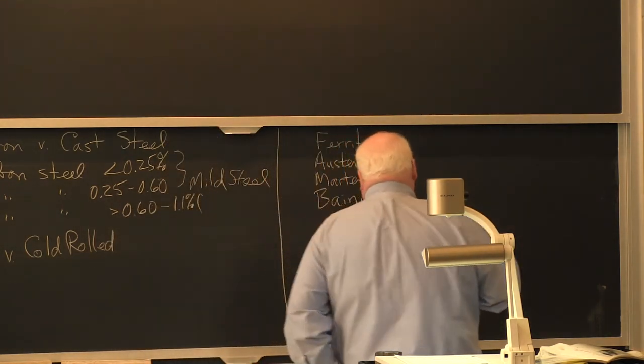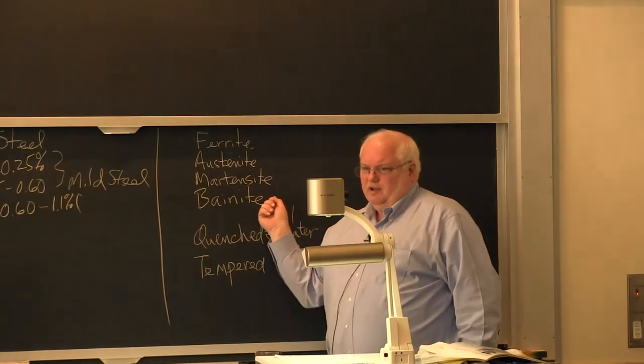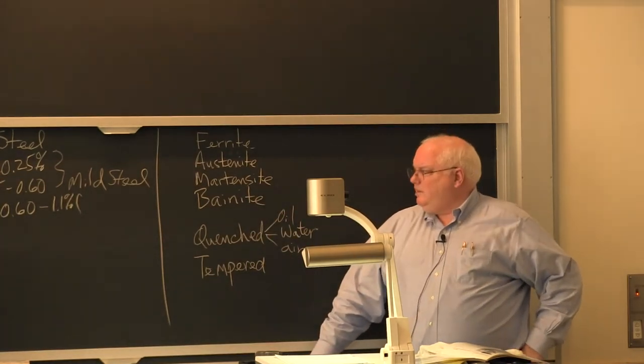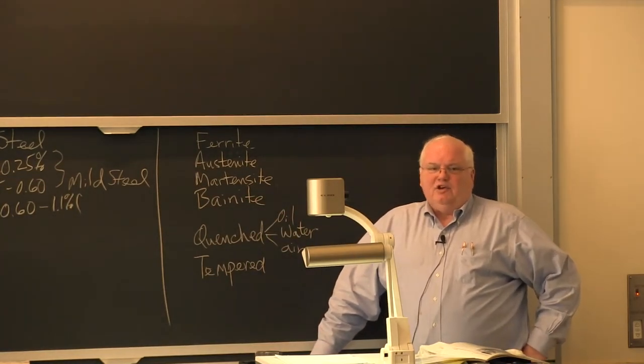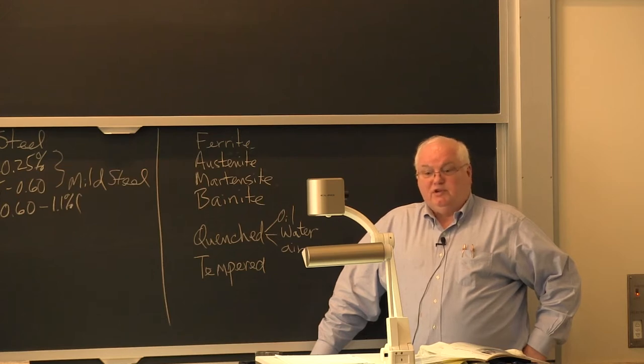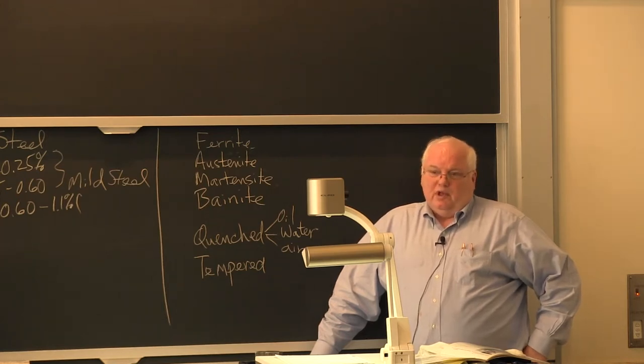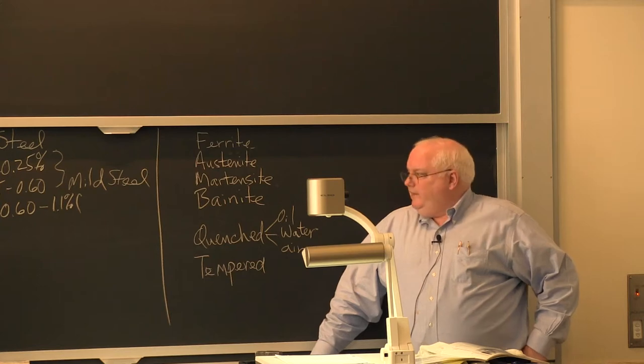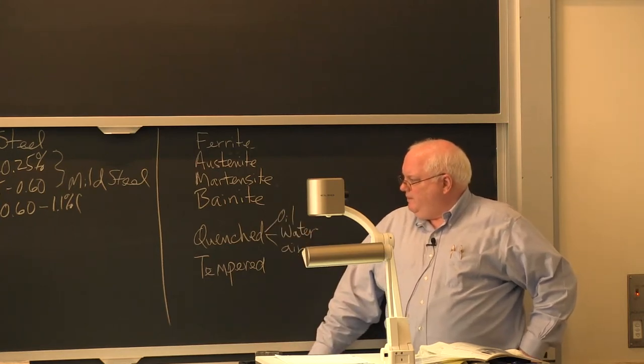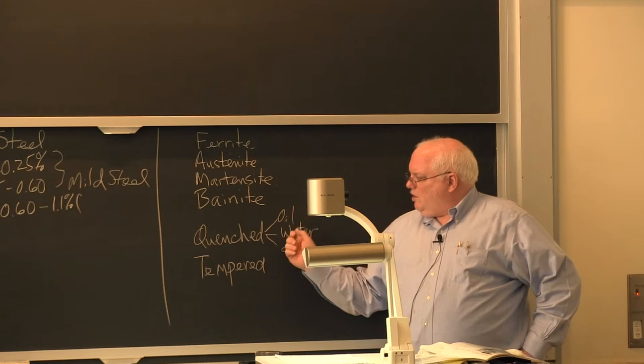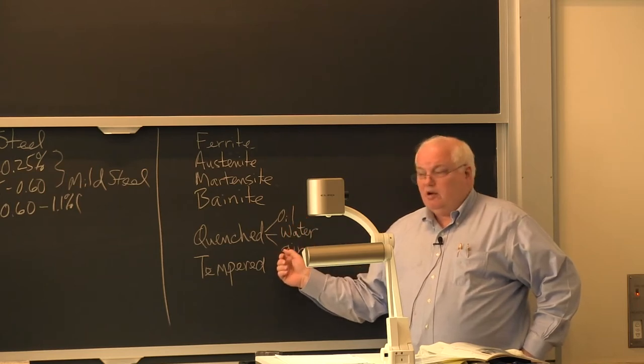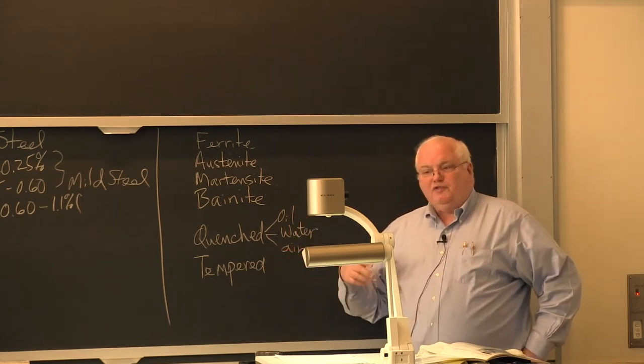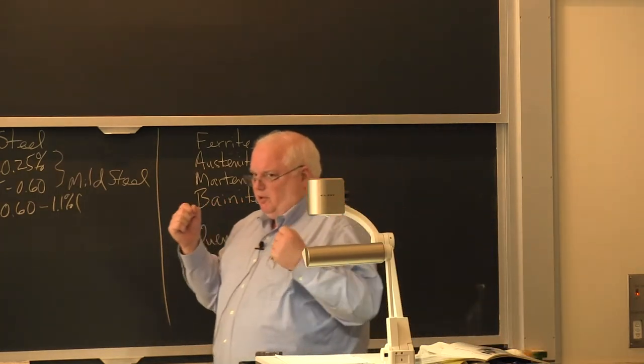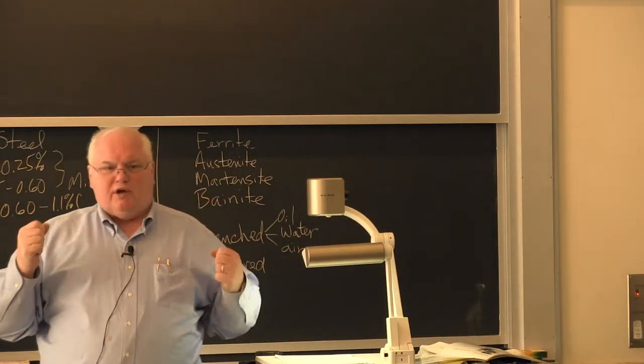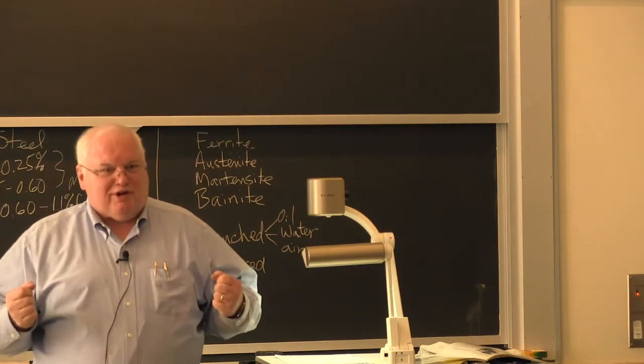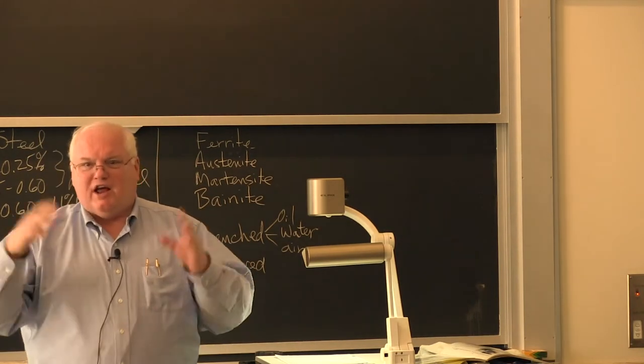Bainite was not discovered or understood until about 1930, and Edgar Bain was a metallurgist at U.S. Steel Research Laboratories, which later were called the Bain Laboratories, and bainite is named after Bain. You can quench in oil, water, or just let it cool in the air, which they call an air quench, and if you do that to martensite, it'll be glass brittle. Actually, it'll be about 10 times tougher than glass, but it's still pretty brittle, okay? You hit it with a hammer and it'll shatter.